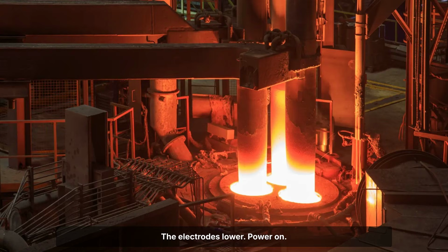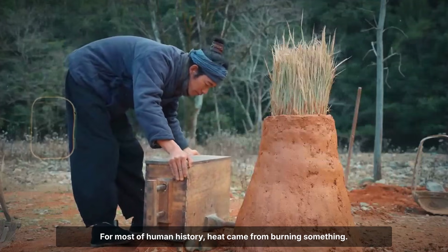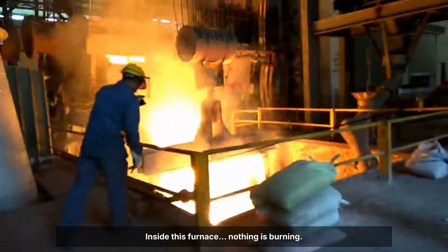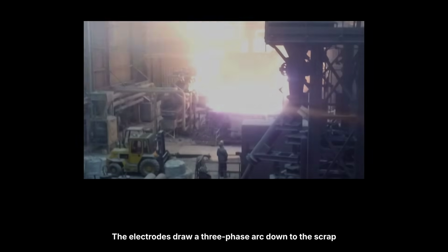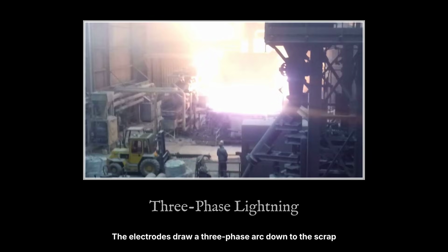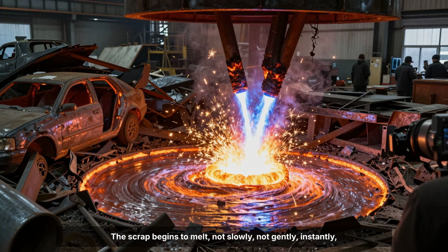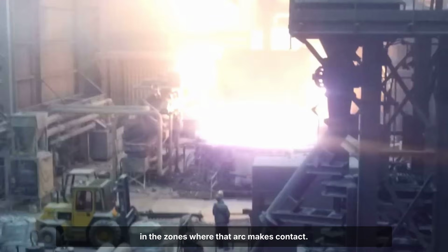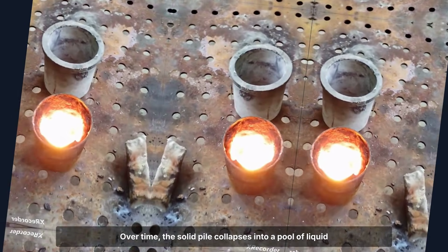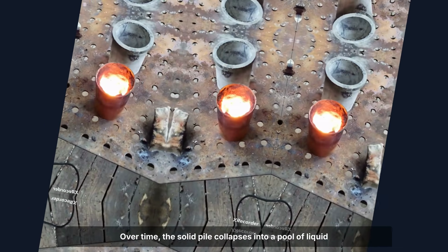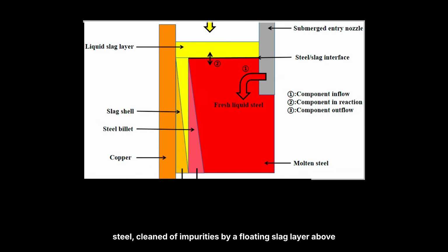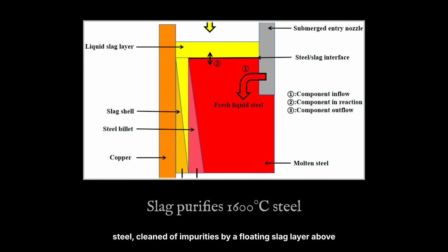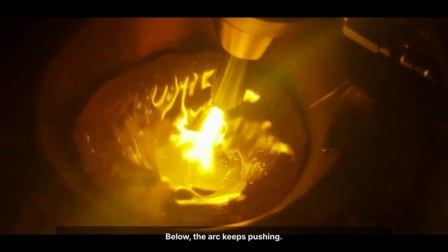The roof closes, the electrodes lower. Power on. For most of human history, heat came from burning something. Inside this furnace, nothing is burning. The electrodes draw a 3-phase arc down to the scrap below. Plasma forms, the scrap begins to melt, not slowly, not gently, instantly, in the zones where that arc makes contact. Over time, the solid pile collapses into a pool of liquid steel, cleaned of impurities by a floating slag layer above it. Below, the arc keeps pushing.